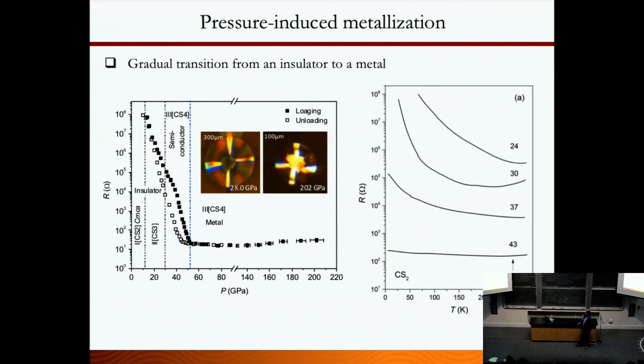Then with this, we did a conductivity measurement. We put in 4 electrodes and measured the conductivity. If you look at the pressure versus resistance, you can see an 8 orders of magnitude difference in resistance while squeezing to higher pressures. It goes from insulator to semiconductor to metal. At low pressures it's not shiny, and at really high pressures, 200 GPa, it's very shiny, as shiny as the platinum electrodes.